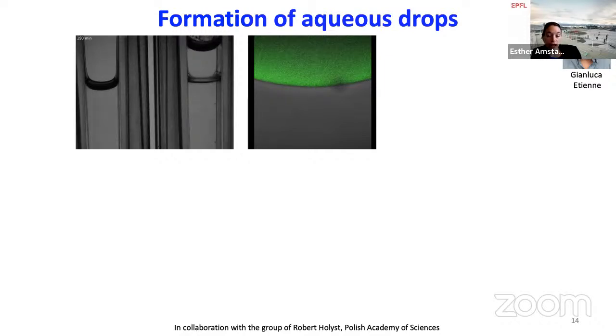So in collaboration with some friends in Poland, we did some fluorescence microscopy analysis, and we saw that micrometer-sized aqueous drops formed at the oil-water interface. So somehow we had a spontaneous emulsification happening in the oil phase that most likely will also happen in the oil drops. And so the question was: if that hypothesis, that spontaneous emulsification at this interface is the reason for the transport that we see, is correct, then the transport of the reagents across these oil phases should scale with the interfacial tension, because this is the energy you need to pay to form these small drops. The higher the interfacial tension, the energetically more expensive it is to form these drops.